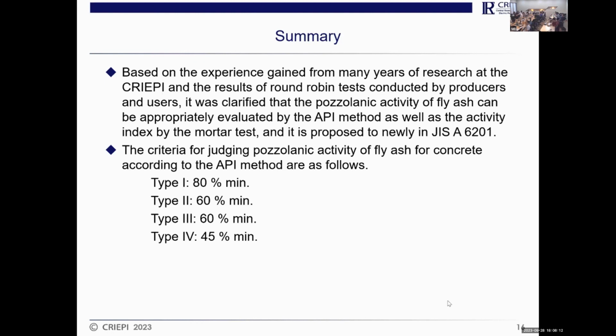Based on the experience gained from many years of research at CRIEPI and the result of the round-robin tests conducted by producers and users, it was clarified that the pozzolanic activity of fly ash can be appropriately evaluated by the API method as well as the activity index by the mortar test. And it is proposed to newly add to JIS A 6201 the criteria for judging pozzolanic activity of fly ash for concrete according to the API method as follows.